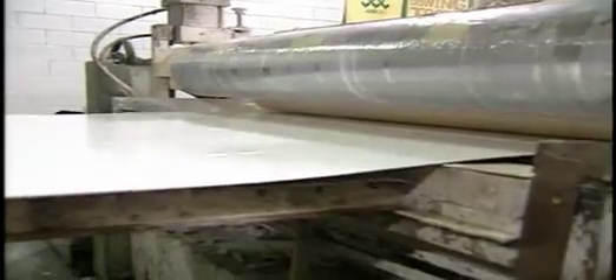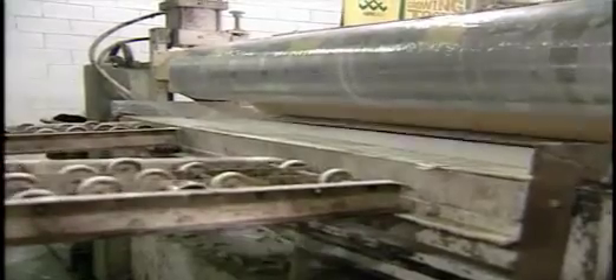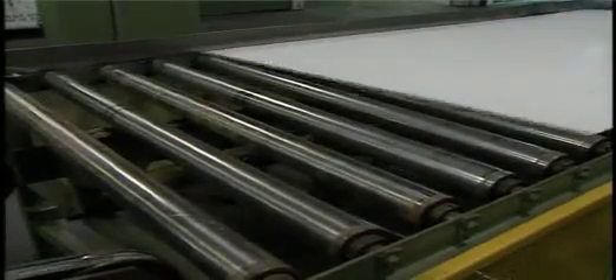If the second roller turns in the same direction as the surface to be coated, the system is referred to as a direct roll coater. If they turn in opposite directions, the system is a reverse roll coater. Transfer efficiency for roller coating is typically greater than 95%.